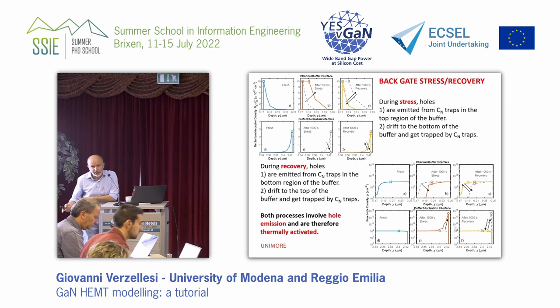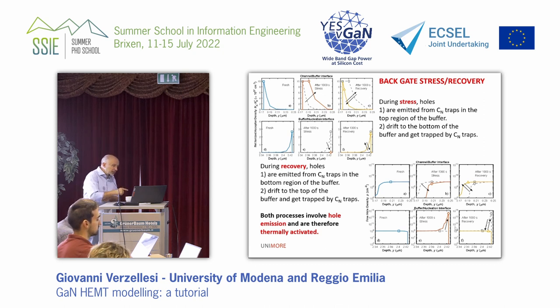And during recovery, you have exactly the opposite processes. So during recovery, holes are emitted from traps in the bottom region of the buffer, drift to the top region of the buffer, and get trapped in the same traps. So both processes involve hole emission. In both processes, there is hole emission, and hole emission is activated thermally by the trap energy itself, 0.8, 0.9.